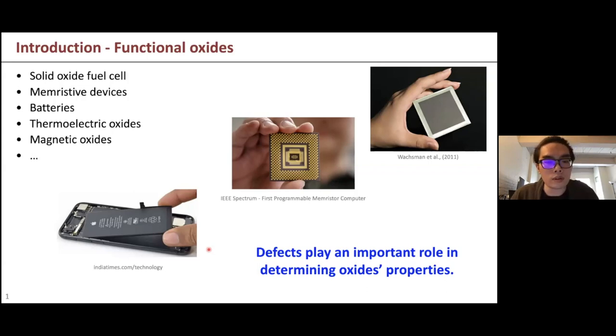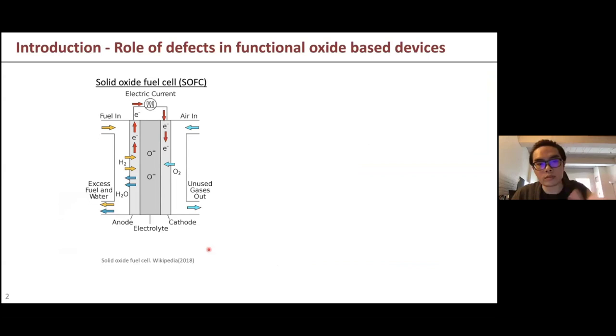So first of all, let me introduce a simple schematic of how the solid oxide fuel cell works. On the left-hand side, you feed in the fuel, in this case hydrogen, which gives out electrons that pass through whatever you want to power up, and then oxygen takes the electrons back. In the middle is an electrolyte, and to form a full circuit, you need oxygen vacancy migration. That's the part we care about more, the solid part, because the higher the mobility of the oxygen vacancy, the higher the efficiency of this whole thing will be.